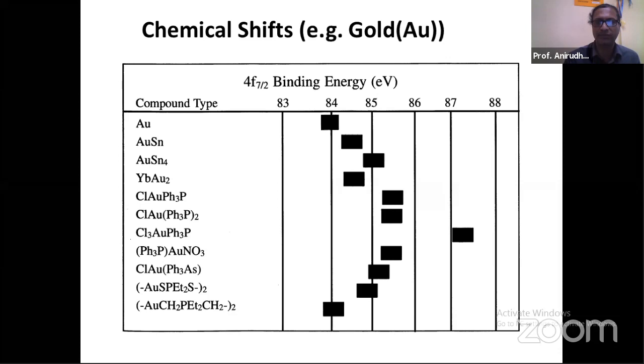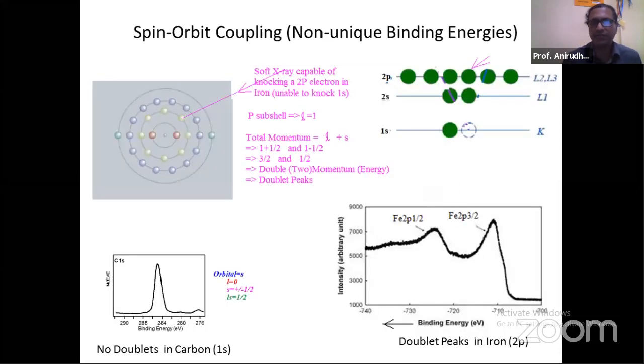Now it has its own consequences. We will see that in the next one. This gives rise to a very interesting result, which is called spin orbit coupling. As tribologists, you may not require the science behind all this, but tomorrow when you subject your sample to a chemistry division for investigation, and you want that analyst or technician to give you XPS information related to iron, he may obviously ask which information you want, whether from Fe 2p 1/2, or Fe 2p 3/2. So we should know what he means by that. What is the difference between Fe 2p 1/2 and Fe 2p 3/2?